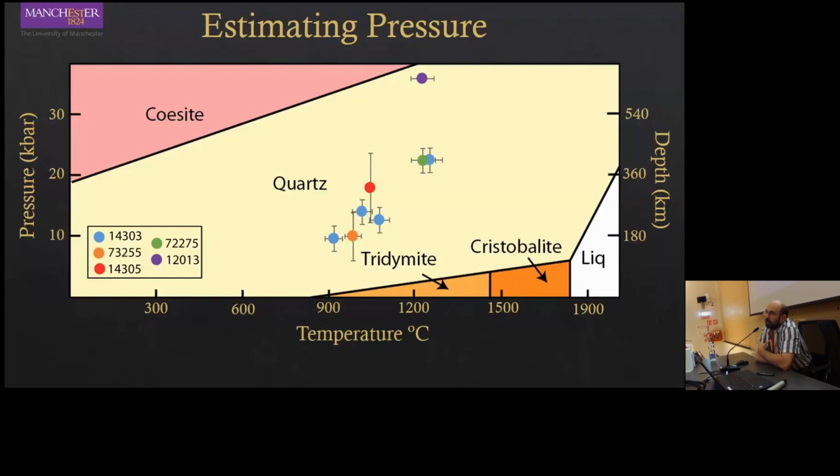And so I think we're sort of confirming this idea that these Apollo granites probably crystallized as tridymite and underwent some kind of later process to convert them into quartz. And I think the important thing that I want to point out in this talk is the fact that at the temperatures that we're talking about here, so temperatures up to 1300 degrees in some cases, tridymite is potentially stable well into the lunar crust, up to 10, 20, 30, 40 kilometers into the lunar crust.